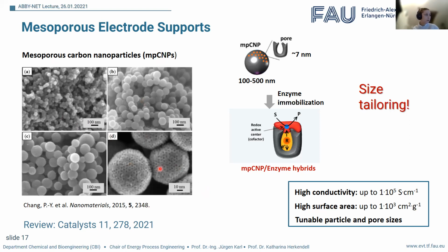Now, mesoporous carbon nanoparticles can be manufactured in many ways, and they have the huge benefit that you can tailor the pore size to whatever you want their function to be. Also, they have very large electrical conductivity, and a major benefit for the capacitance of any enzymatic biofuel cell is the extremely large surface area. What we did with these pores, which in our case had an average diameter of 7 nanometers, was utilize them not, as in many cases, for the enzyme stabilization itself, but for the incorporation of relay molecules, which means we would introduce mediators inside the pores to shuttle electrons between the active center and the electrode surface.